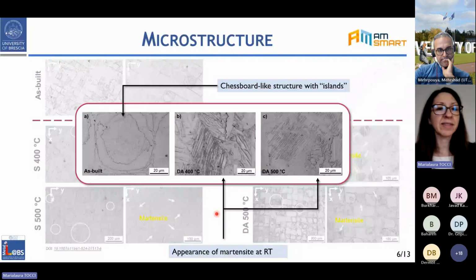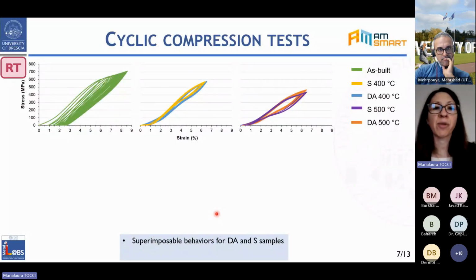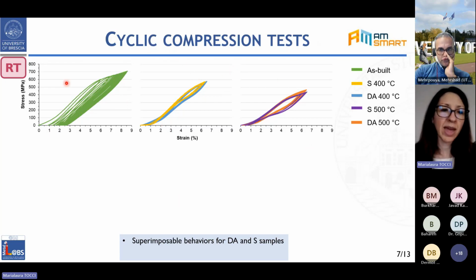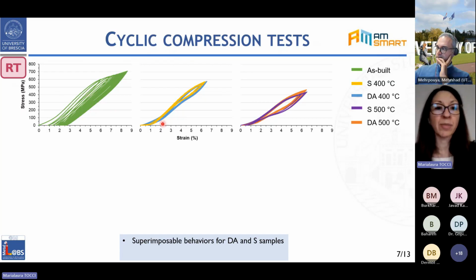Moving to the mechanical characterization, here you can see the stress strain curves from the cyclic compression tests carried out at room temperature. It is evident, if we compare the behavior of the material after heat treatment with the behavior under as-built condition, that the superelastic behavior improves after the heat treatment. And it can also be appreciated, if we again compare the alternative with and without the solution treatment, that we found almost superimposable, extremely similar behavior, again suggesting that solution treatment does not play a fundamental role in determining the superelastic behavior of the material.